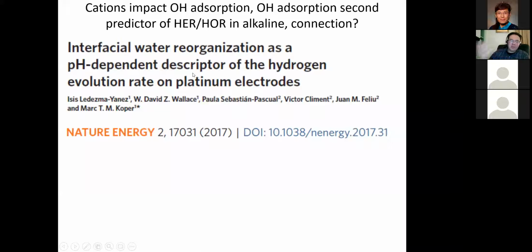I told you solvation, the interaction with water, was very important to dictating hydroxide adsorption, and that the cations were messing with that solvation. And Marc's group proposed that maybe what's also happening here is that when we go from acid to base, the ability of water in the interface to move is really what's changing. In other words, hydroxide binding maybe isn't the descriptor, or it's a descriptor, but it's mechanistically not really linked. They're just two different features of measuring how water is behaving at the surface.